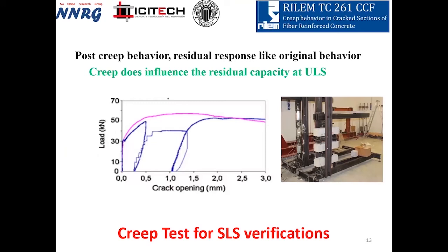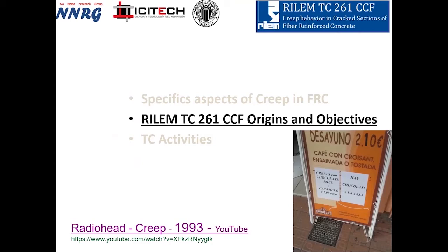There is a final question that is important to note for all the methodologies we know in the bibliography: no matter what the methodology is, after a creep test, a long-term applied load, if we analyze the residual capacity of the elements, you have the same capacity as the elements that were not pre-cracked and were not subjected to the creep test. Then for the ultimate limit state, if you don't have a problem in service time, you always have the same ultimate capacity.